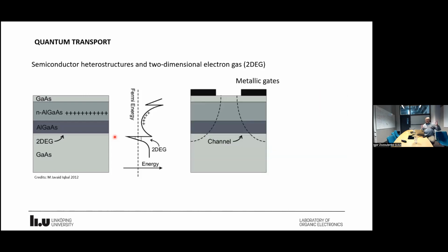And then using this two-dimensional electron gas, you can create various structures. For example, if you put metallic gates on the top, and then you apply a negative gate voltage, you will remove electrons underneath the gates, and then you can create channels inside your structure. So the electrons can go only in these channels.